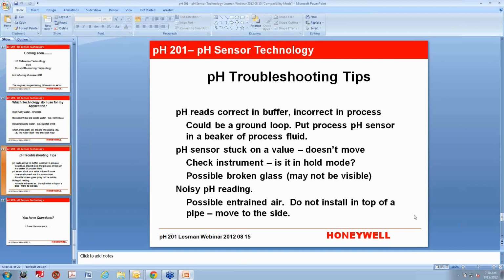Noisy pH readings are oftentimes caused by entrained air. Lots of processes have air bubbles in them. It's pretty common. And air bubbles, because they're lighter than the rest of the process, will float to the top. So you don't want to install a pH sensor, as a matter of course, at the 12 o'clock position in a horizontal pipe, if you think of it as a clock, where the top is 12. If you install the pH sensor directly at the top and you have entrained air, all those bubbles are rising to the surface, and you can't measure the pH of a vapor or of air. You have to be in a liquid with these devices. It gives a no-signal pH signal, so what you see is the pH jumping all around because it's trying to measure air and it can't.